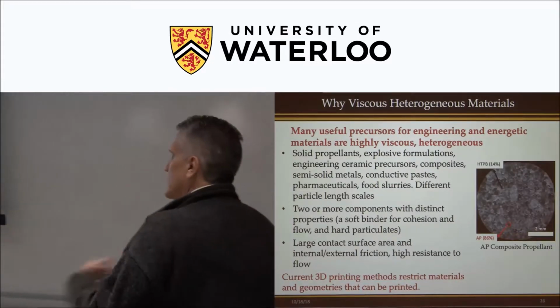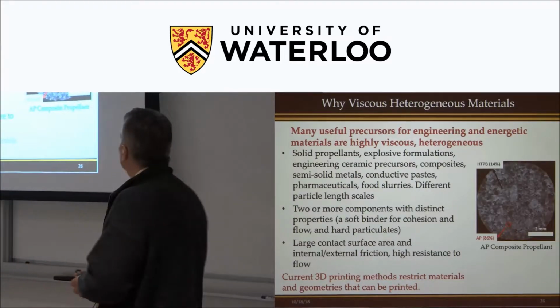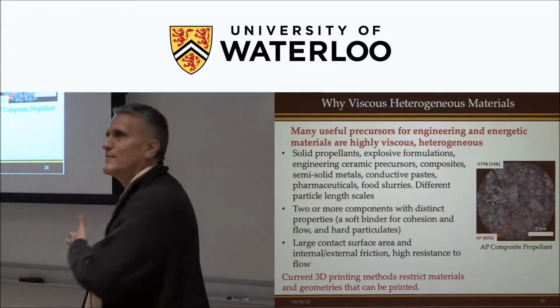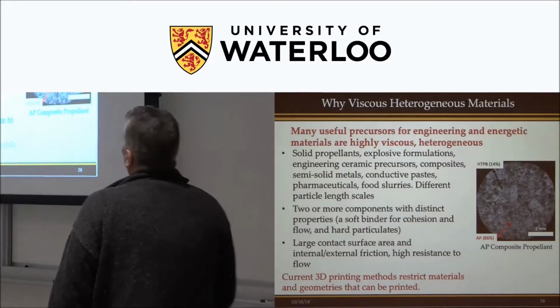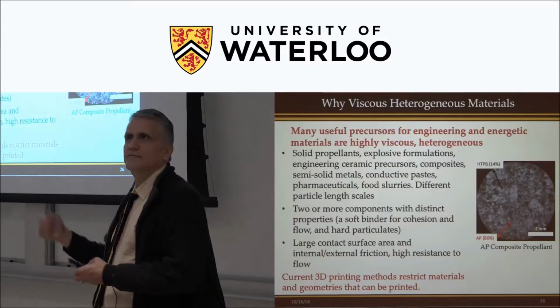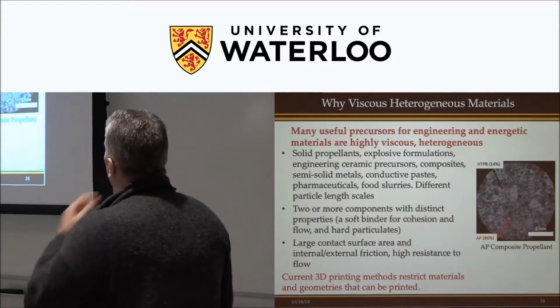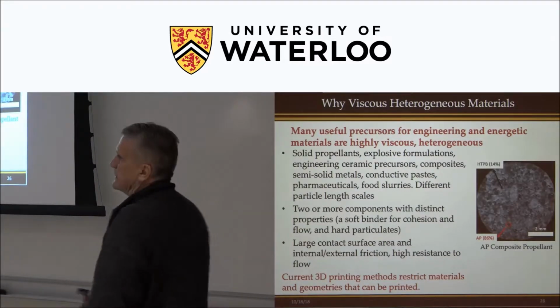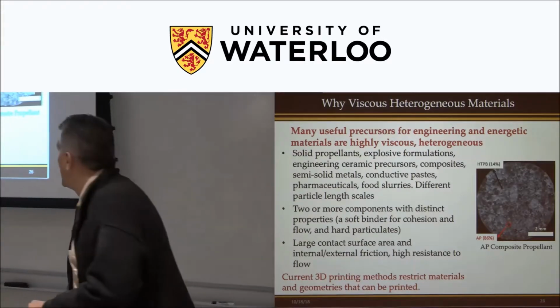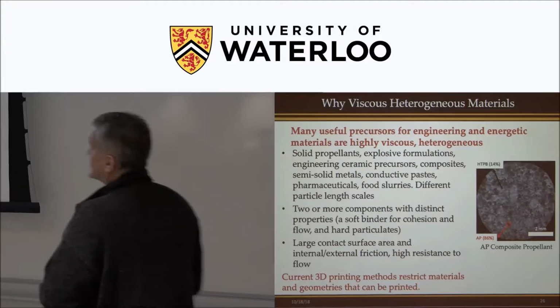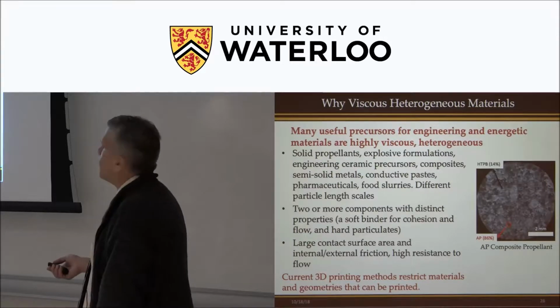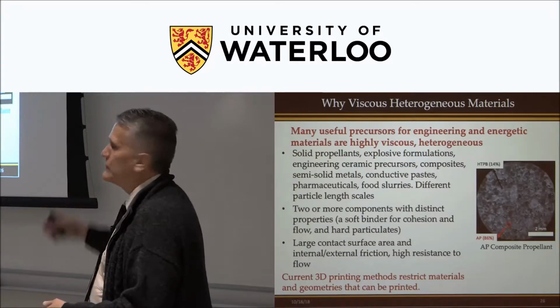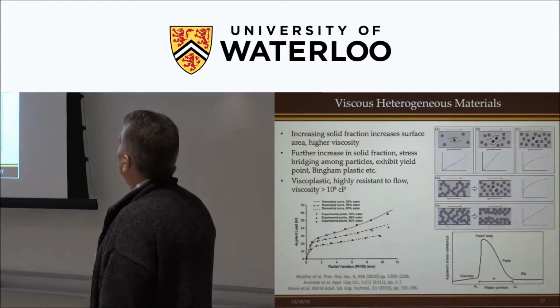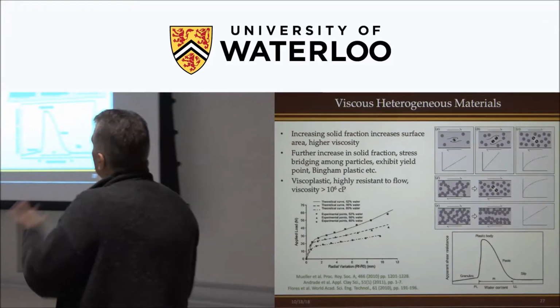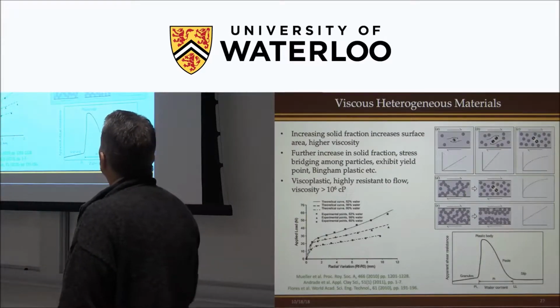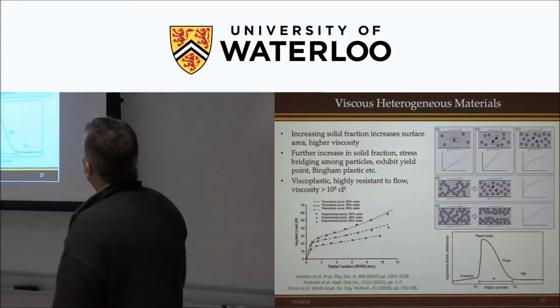These materials are highly viscous. When you mix up a solid propellant, think of that as like cookie dough. So it's quite viscous, especially if you're trying to maximize the amount of sugar in your cookies, right? And we're trying to maximize the amount of oxidizer in our propellants for performance. Well, that works against being able to deposit that and build up 3D structures. So that's challenging. And the current 3D printing methods restrict the kinds of materials. We really can't use the binder that we'd like, the polymeric component holding this together, because the viscosity is too high. We'd like something that's thermal softening that will work better, or you will have to restrict the amount of solids that we put in the propellant so that we have a poor performing propellant. Increasing the solid fraction increases the surface area that has to be bound together with the binder. The viscosity increases with that, and I think I'll move along.